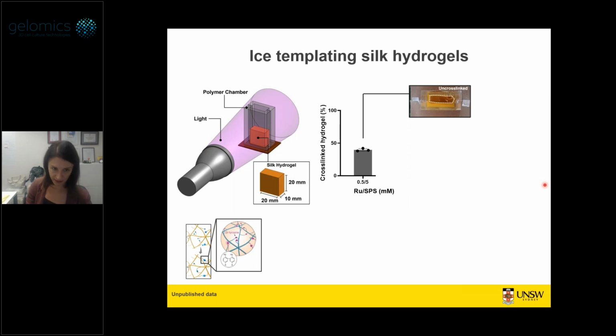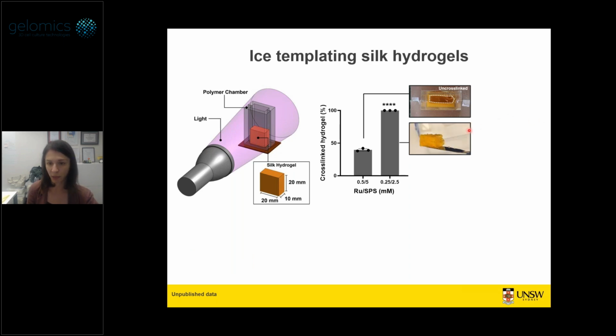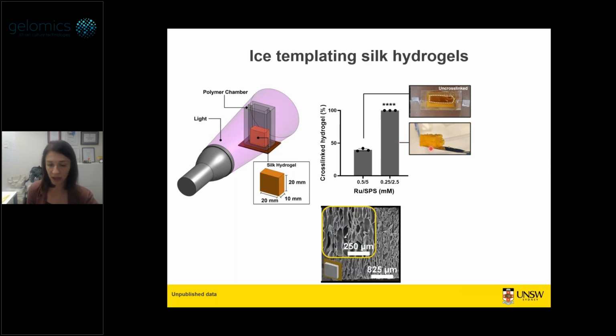But when we started freezing hydrogels, we actually had to optimize our cross-linking again so that we can be freezing directly in these molds that we ice template our silk in. And that took a little bit of optimization because our normal optimized cross-linking conditions of ruthenium and SPS for initiator were not actually working. We were getting lots of uncross-linked silk. So it took a few months to actually optimize this, but we can now make these very large constructs that we can take out and manipulate if we need to, not that we do, but really nice cross-linking in this system.